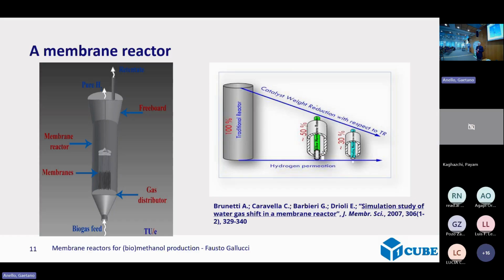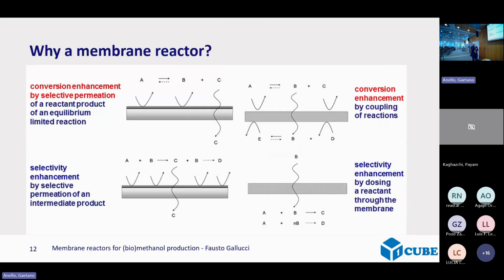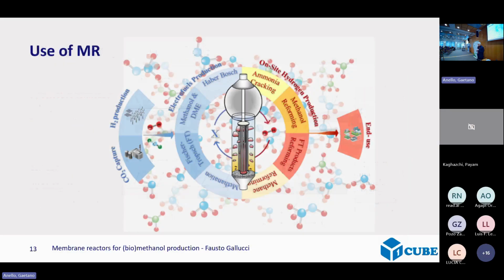So you have to have a problem in the reaction itself. And most of the time, it works when you have, for example, equilibrium reactions. When you have an equilibrium reaction, you can optimize the catalyst, you can do core shell, you can do whatever you want, but you reach the equilibrium if you fix temperature and pressure. In that case, if you extract a product, then you can shift the equilibrium. Now, what is nice is that all the reactions that involve hydrogen are equilibrium reactions. So either you produce hydrogen or you use hydrogen, then it is a typical example where you can use membrane reactors. And one of our PhD students made this very nice picture where you see all the possibilities where you can use a membrane reactor, whether to take CO2 and hydrogen and form something, up to taking, for example, ammonia and getting back the hydrogen.